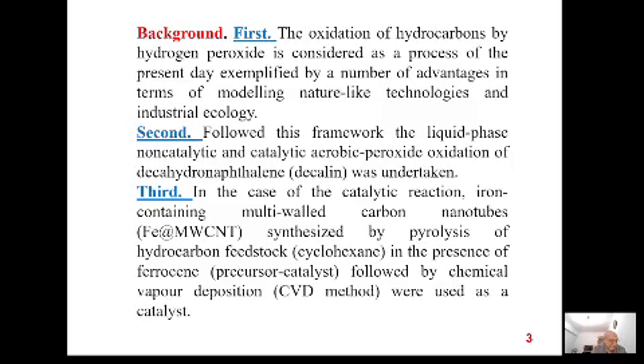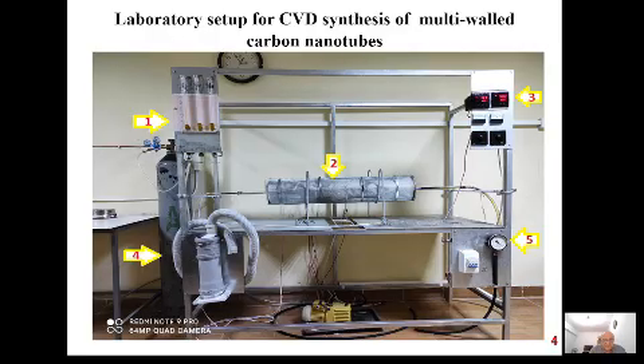In the case of the catalytic reaction, iron containing multi-walled carbon nanotubes, produced by pyrolysis of hydrocarbon feedstock, cyclohexane, in the presence of ferrocene as precursor catalyst, followed by chemical vapor deposition, were used as a catalyst. The next slide represents the laboratory pyrolytic setup constructed in the laboratory and used for CVD synthesis of multi-walled carbon nanotubes. The details of the method for obtaining metal-containing carbon nanotubes follow.